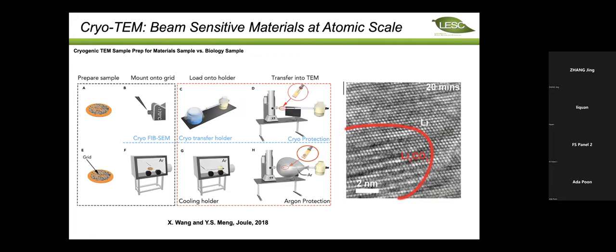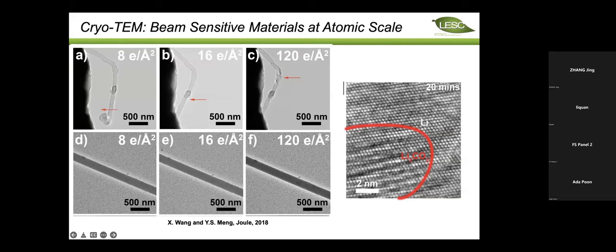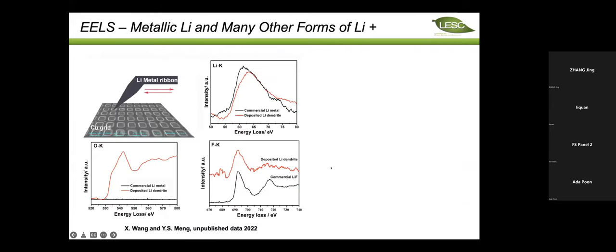But in reality, the electrochemically deposited lithium is often covered by this kind of insulator species, and they impose very, very difficult imaging. So basically you have to go to low temperature to reduce the reactivity of this lithium SEI component under the TEM. So you can use very low dosage electrons to image the lithium metal with high quality.